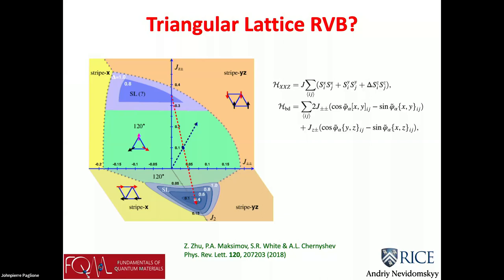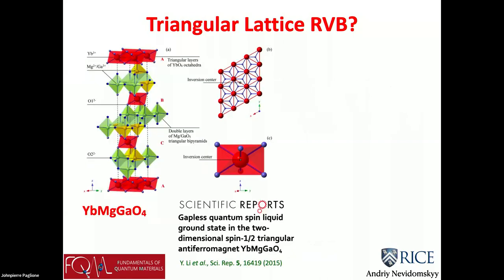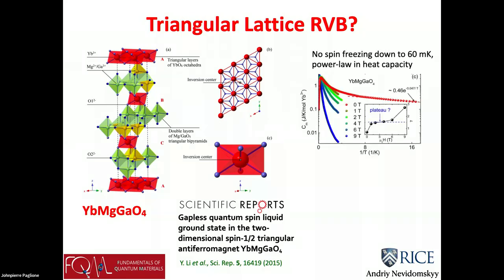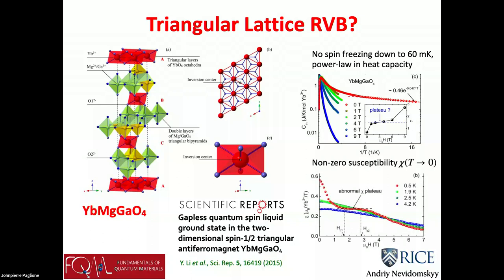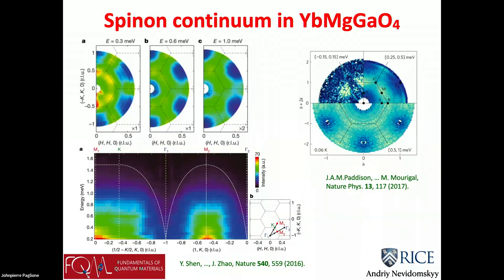You need to crank up certain quantum terms that you could do here. I won't go into details. This is from the paper by Sasha Chernyshev. There was one particular example, an ytterbium-based material, which is very promising. It's a layered compound. It does look like a perfect undistorted triangular lattice. If you look at, for instance, specific heat and susceptibility, they show strange power laws that you can see from here. So there is a power law over here, there is some abnormal plateau. And then if you measure inelastic neutron scattering, you find again a spectrum, both in the energy and momentum space, of diffuse excitations.